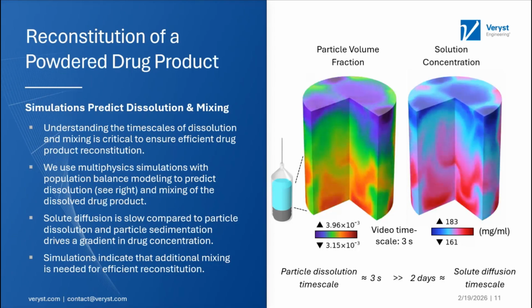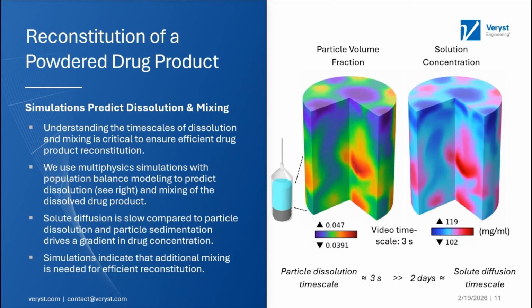So to model the dissolution of the lyophilized drug product and mixing of the dissolved drug product, we developed a COMSOL Multiphysics model with coupled flow, species transport, and the population balance equation. We used a typical autoinjector chamber geometry, and we predicted the transient dissolution and solute transport during reconstitution. As drug particles dissolve, the solubilized drug concentration increases.